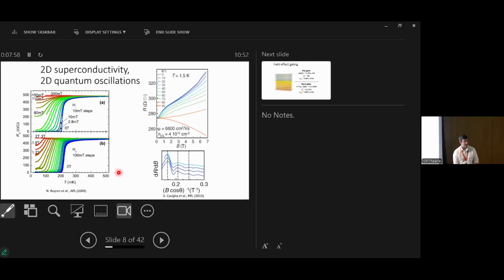And it turned out to be a two-dimensional superconductor. So here are just some resistance versus temperature plots in various magnetic fields. And this was work done by Jean-Marc Triscone's group in Geneva. They basically showed that in order to destroy the superconductivity, you need some magnetic field, but the magnetic field required in the plane of the sample, that's this one, Tesla level, compared to perpendicular to the layers, 300 millitesla, so much smaller, there's a big difference suggestive of a very thin layer of superconductor.